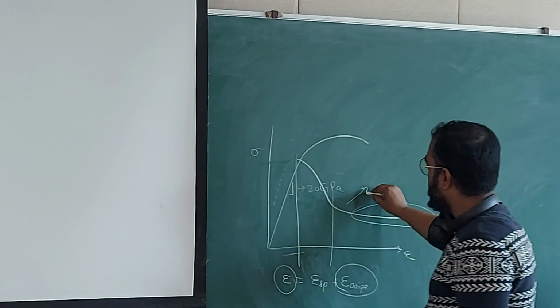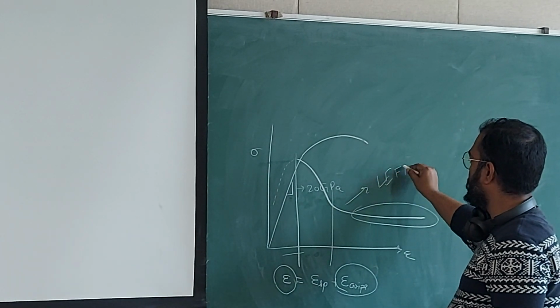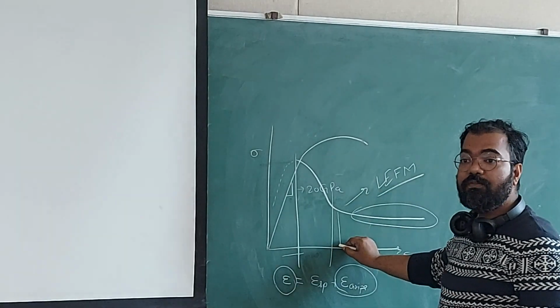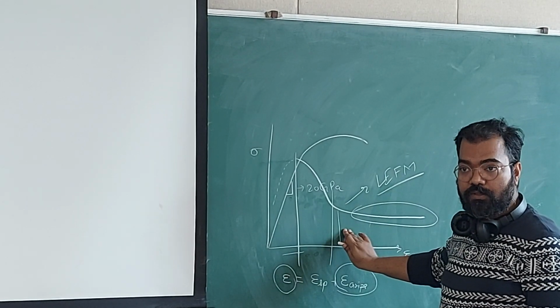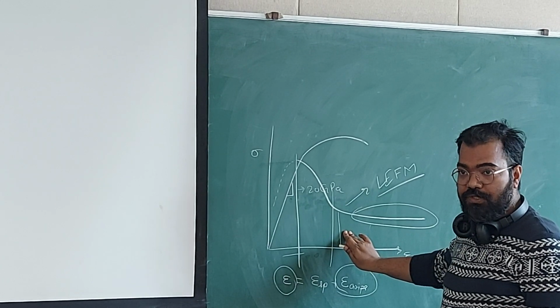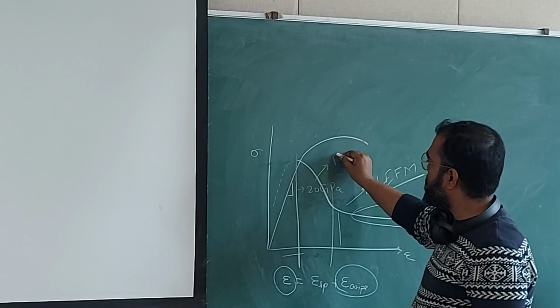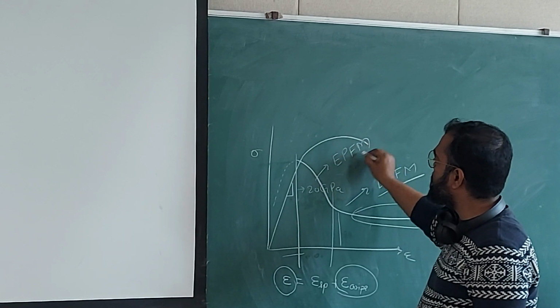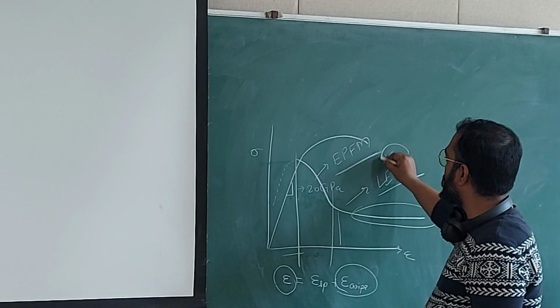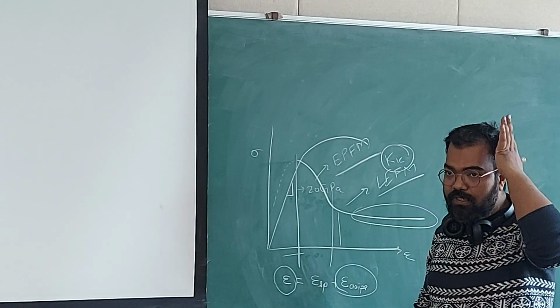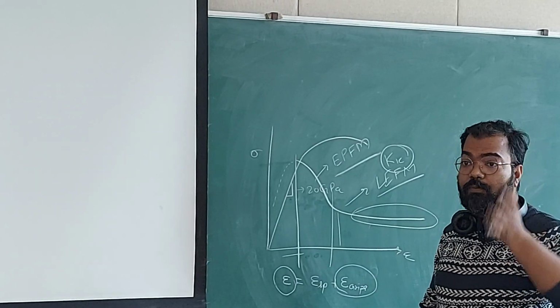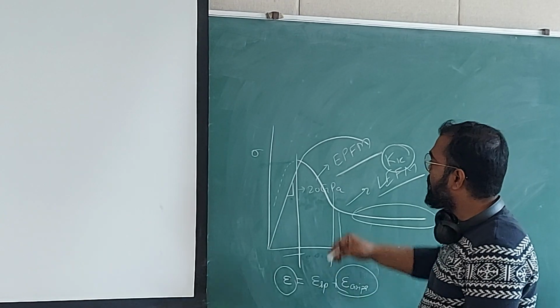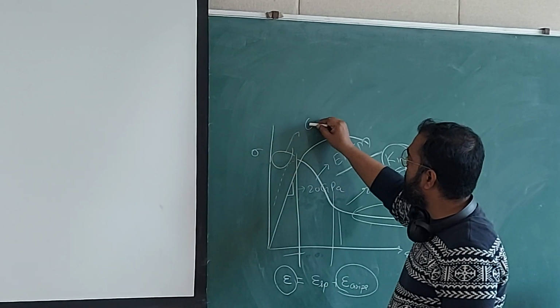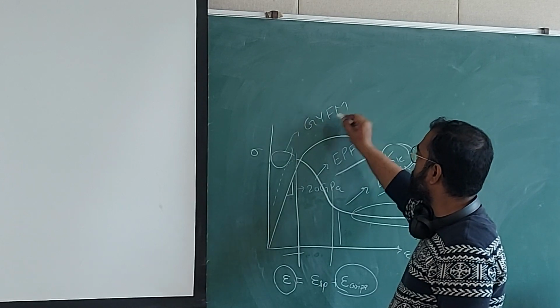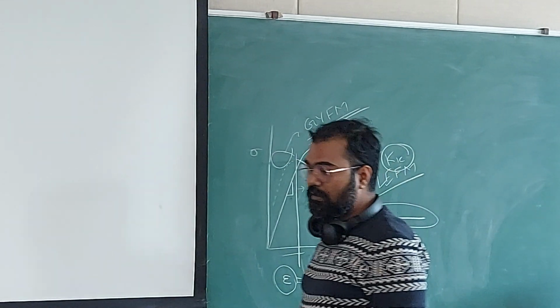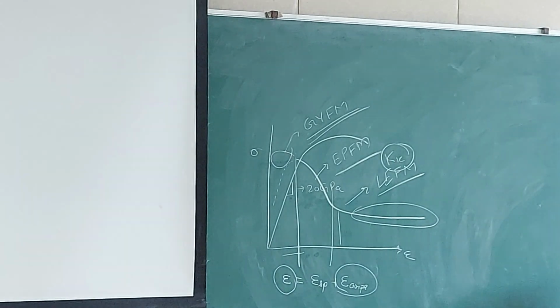This region is LEFM, where plastic zone is significantly smaller and you can ensure plane strain condition. In this region, it is elastic plastic fracture mechanics, where plasticity is significant. K1c is not so much valid there. You can still measure it, but that will be plane stress condition, or somewhere in between plane stress and plane strain condition. And this region is called general yielding fracture mechanics, GYFM, which is the case for thin sheets. And we close the session today.